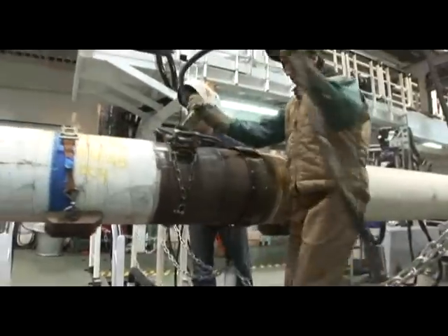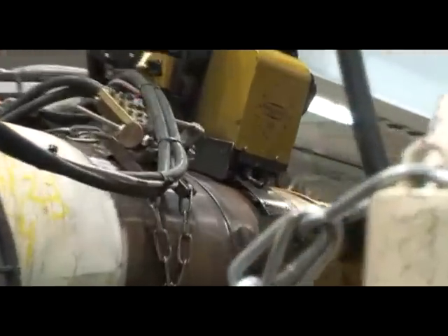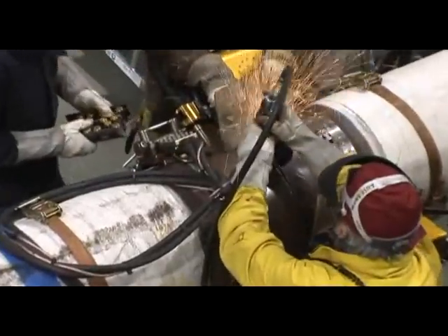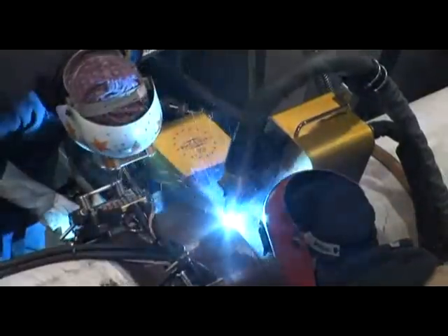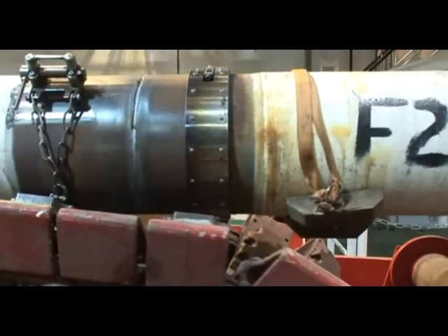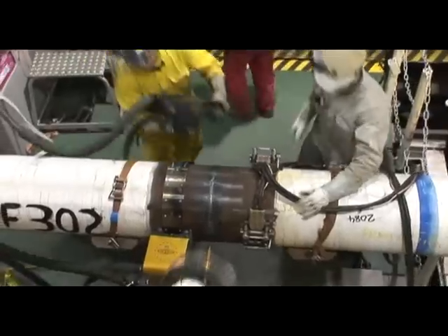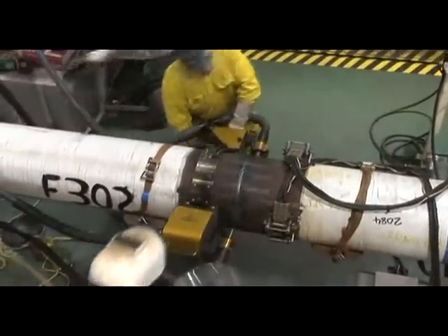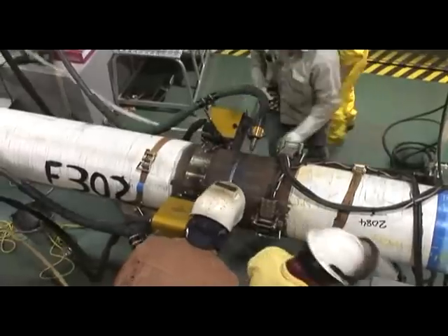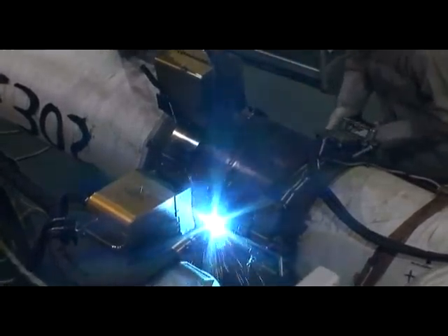To fill up the complete weld, more welding passes are needed, and the pipe section is moved to the next welding station. For this project, ALLSEAS used its Phoenix Gold welding system, consisting of 2 automatic welding bugs at each station. For bigger pipe sizes, Phoenix Gold enables 2 welding passes in a run instead of 1, which considerably reduces welding time. At the next stations, the hot pass and fillers are welded using Phoenix Gold automatic welding. After the filler welds, the welding is completed with an end cap weld.